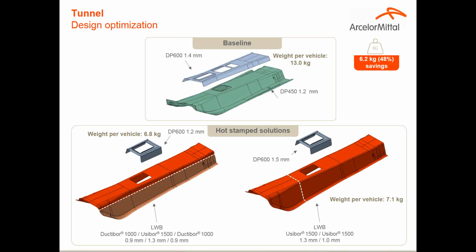We can make two proposals, one with longitudinal welds on the left-hand side, and one with transversal welds on the right-hand side. In both cases, we proposed, and this one is in this specific slide, hot stamped solutions, but why not cold stamped? With the third generation grade, we can anyway improve formability, and we can try to meet the requirements. And as you see, anyway, some patches are needed, but localized and much lighter than the baseline.